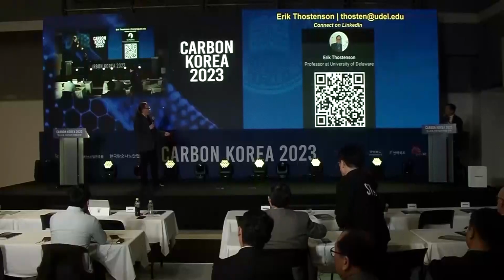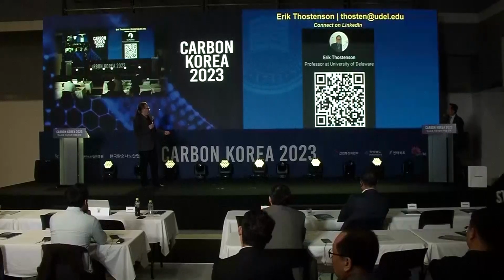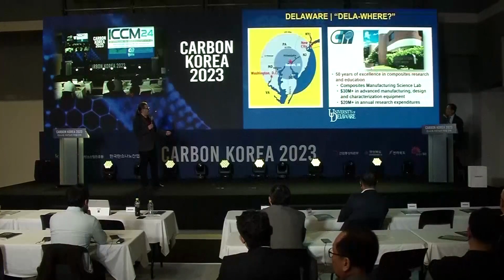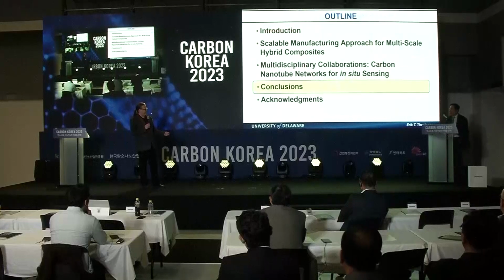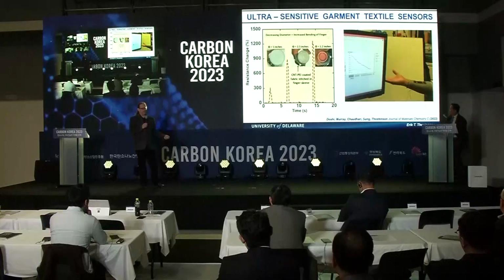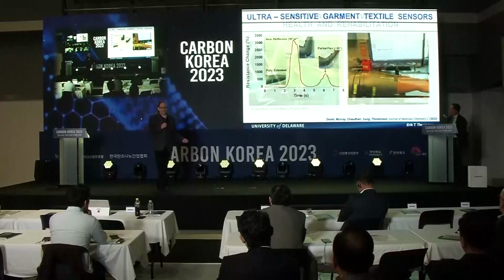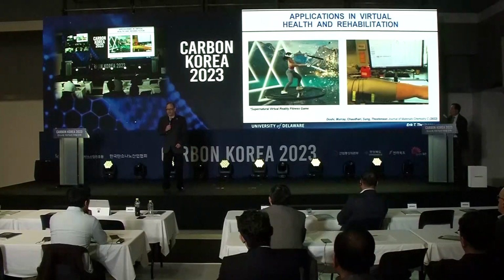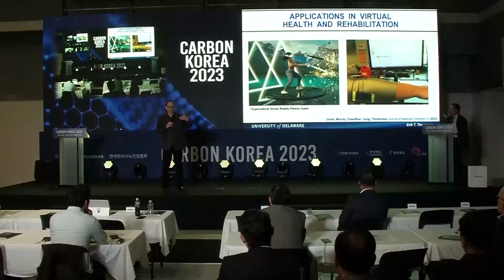So it was a compact tension specimen. That was our work where we validated it in the lab. One of the key parts, and I kind of skipped over that slide, was that the addition of the composite resulted in a 400 to 500% increase in the fatigue life. But the durability of the sensor, we've evaluated that in the field, looking at that crack growth, and also could monitor that. So, does that cover it?